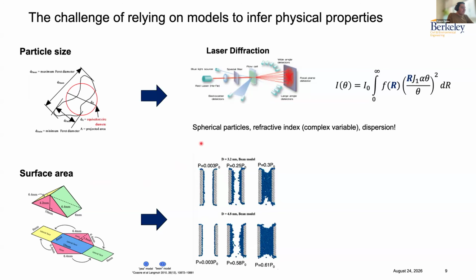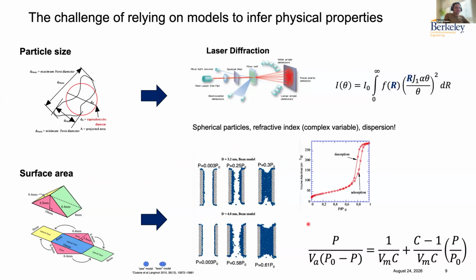So we assume a monolayer or a multi-layer surface coverage of an adsorbate on an adsorbent, as we are seeing here for a silicate surface, much simpler than the materials that we work with regularly. And then we obtain this adsorption and desorption isotherm. Luckily, we had this very smart group of scientists back in the past, Brunauer, Emmett, and Teller, that realized that by rewriting the equation for this isotherm in a smart way, which is this representation here, the isotherm equation could be linearized. And this is what we call today the BET model.